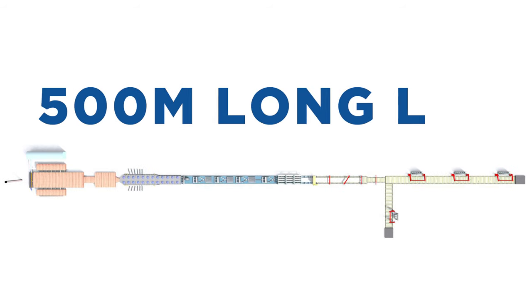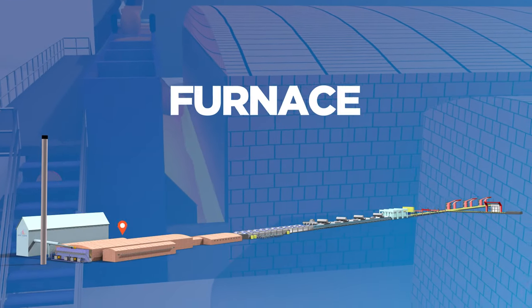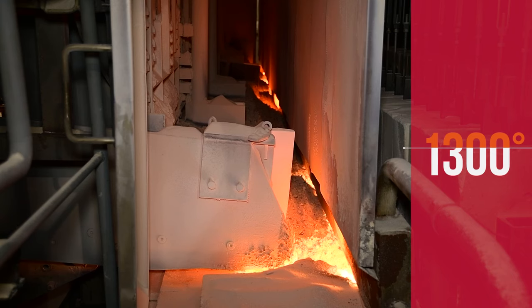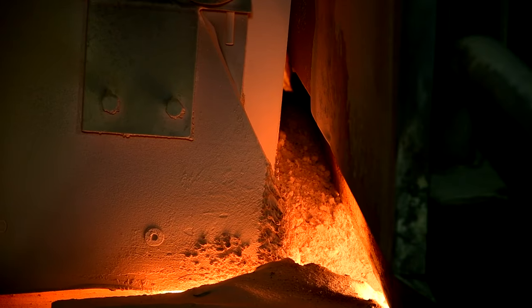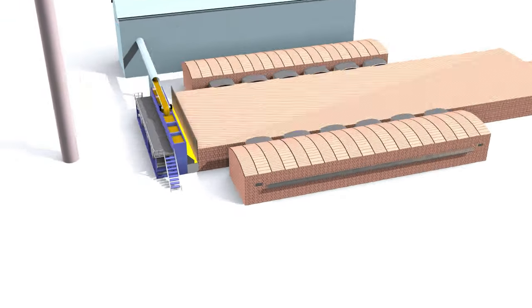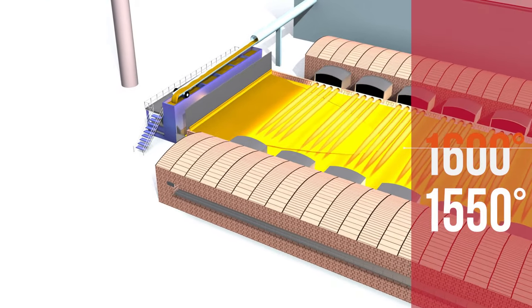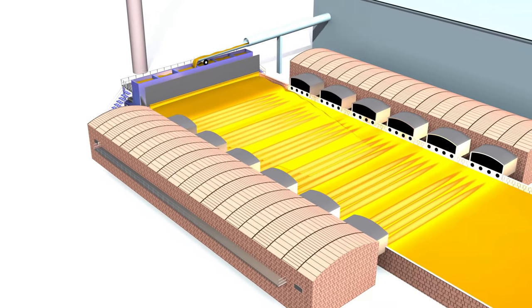During the process, a flat glass ribbon of uniform thickness is formed on a 500-meter-long line. The batch charger regularly lays down raw materials at the furnace entrance on a part of the line called the doghouse. The raw materials drop onto the 1,300 degrees Celsius molten glass already contained in that area and are continuously pushed inside. In the melting zone, the batch of mixed raw materials melts at a temperature of 1,550 to 1,600 degrees Celsius until it becomes liquid and merges.